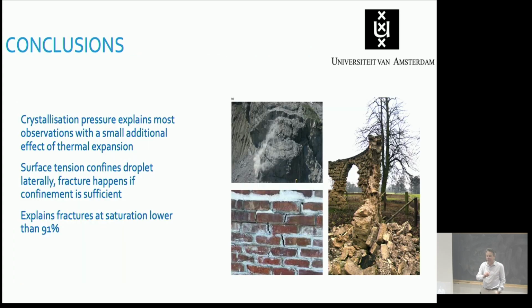And so without any PowerPoint problems, I've come to my conclusion, well in time for lunch. But I think that the concept of the crystallization pressure explains most of our observations, but thermal expansion could also play a role in the observed damage in the outdoors. What is important in the porous media is that you have small pores in which there's pockets of liquid, preferably with a contact angle if you want damage. Preferably with a contact angle of 90 degrees, because that exerts a maximum pressure onto the walls.